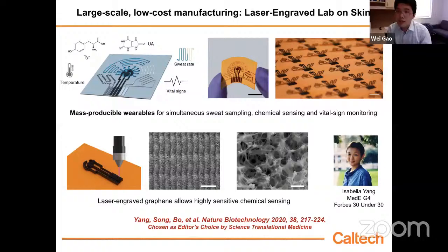That's why recently we proposed this platform, large scale, low cost manufacturing of wearable sensors using laser engraving. CO2 laser cutting is well known to be able to introduce carbonized structure, like graphene structure, on the surface of certain substrates such as polyimide. Taking advantage of this, we can pattern graphene-based biosensors on the surface of polyimide. In this case, you don't need anything else. You just need the polyimide and the CO2 laser cutter. Now program the laser and you can pattern this graphene structure.